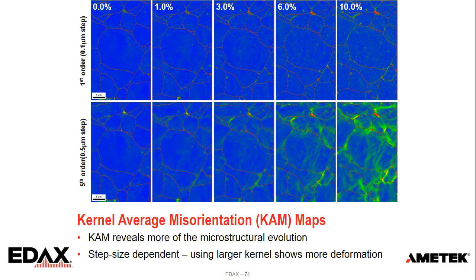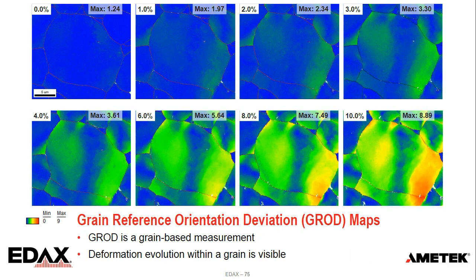When we're looking at these point-to-point misorientations, it can be very dependent on step size and the size of the misorientation gradient. If our step size measures things with a finer precision than we can measure, we'll see a little bit more blue. That's why we can expand the size of these kernels to see the misorientations more clearly. And then we could use something like our GROD maps to show a grain-based measurement. So we see how that particular grain we're focused on bends and evolves as a function of strain.